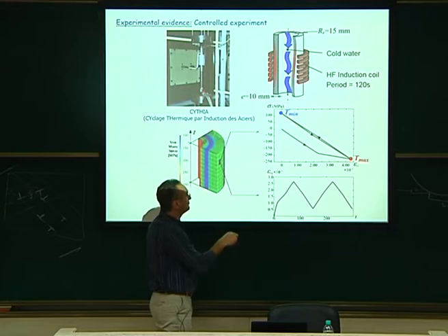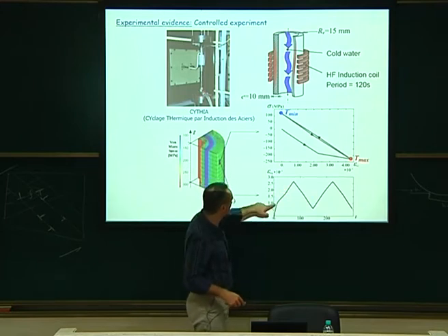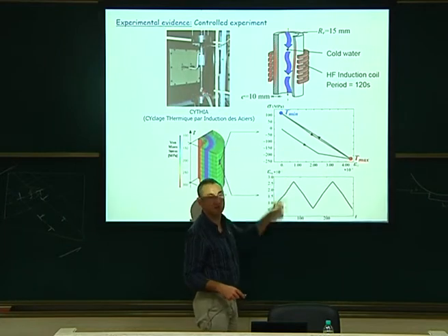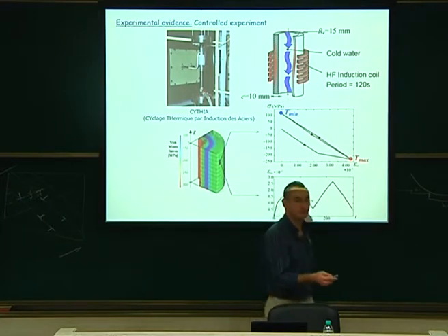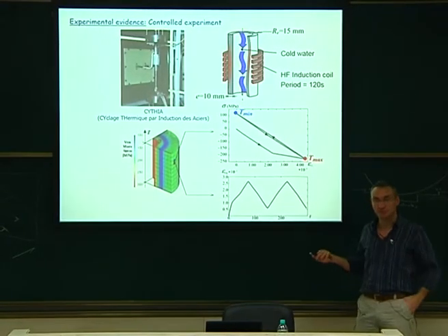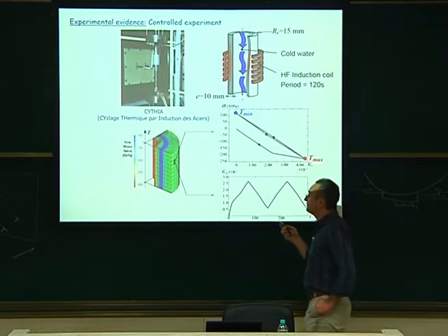And during the cycle, if you compute the plastic strain, you have a very small plastic strain, which is like that, oscillating between 1 and 3 times 10 to the minus 3. You don't see it clearly here, but it's 10 to the minus 3, so it's 0.3%. It's very small deformation. So this is very good for dislocation dynamics. 0.3%, this is something I can achieve, okay? So we are happy with that.